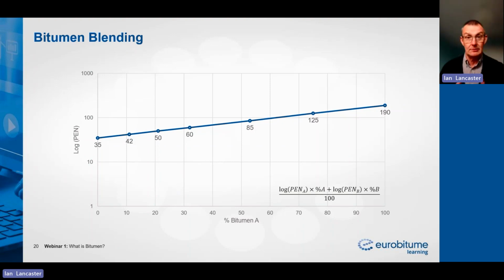Now, I want to introduce a note of caution here, and this is very, very important: this blending graph that you can see in front of you and the equation down at the bottom of the screen is only applicable to unmodified bitumens, and equally it's only applicable to materials of known origin. So it's important to remember that if you have developed a blending chart like this one for two different grades of bitumen of known origin, and you take a bitumen of unknown origin, it may well not follow those blending rules. So it's very important to recalculate the blending chart and make sure all of the rules that you've already established actually work. That's a critical takeaway from the session today: the blending chart is only applicable to unmodified bitumens, and only applicable to materials of known origin.